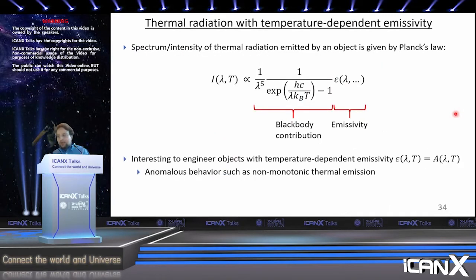Okay, so now I want to change gears a little bit and talk about engineering of thermal emission rather than measurement of thermal emission. So remember that the spectrum and intensity of thermal radiation emitted by an object is governed by Planck's law, and we have this emissivity correction over here. And remember that the emissivity can depend on many different things like wavelength, polarization, emission angle and so forth. And it's interesting to consider a situation where objects have an emissivity that's temperature dependent. So essentially you have an absorptivity that's temperature dependent and therefore an emissivity that's temperature dependent.